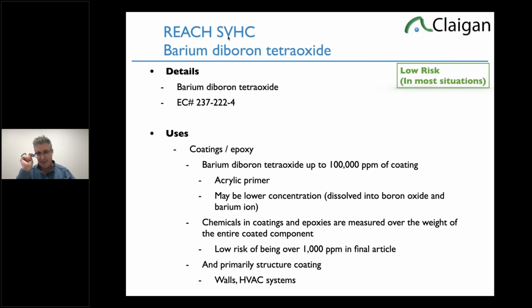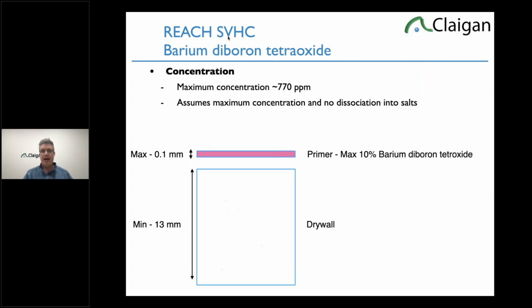The main reason it's delayed is this chemical. It's a very complicated one to explain. It's barium diboron tetraoxide. It can be up to 10%, 100,000 ppm coating, but it's an acrylic primer, and it's structural. So you're looking at mostly walls. We don't see acrylic paint very often on physical products. But the way it works out is even if it's up to about 10% barium diboron tetraoxide, which is normally much lower.